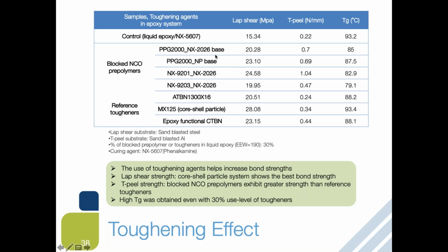So in this study, we basically compare performance of the prepolymer against very well-known tougheners, ATBN, core shell particle, or epoxy functionalized CTBN. Once again, there's a control system, which is liquid epoxy with the high strength phenalkamine curing agents. So there's control data of lap shear, T-peel and Tg. And then now we added 30% of these ingredients, partially replacing liquid epoxy.